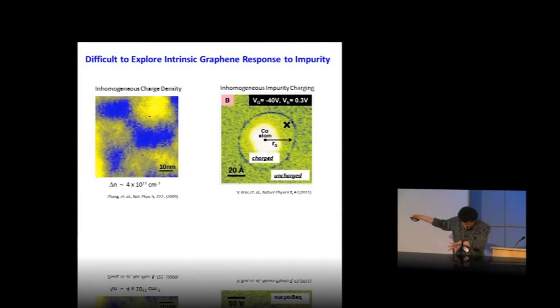Another issue that we have, a problem we have with cobalt atoms, is that the impurity itself has what we call an inhomogeneous charge state. And what I mean by that is that we can set the charge state of the atom with the back gate, but then we want to map what the electrons are doing around it in the graphene. But the problem we have is that sometimes the STM tip will cause the charge state of the atom to switch. I mentioned that to you earlier. And so we have trouble then mapping what's happening around the impurity, because sometimes the impurity's charge will switch.